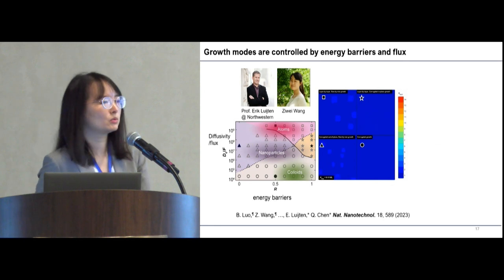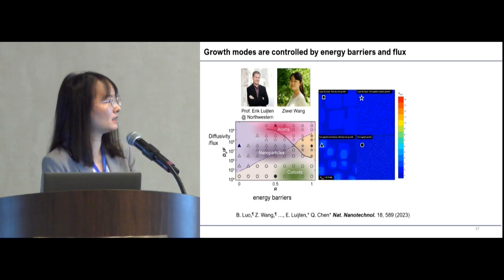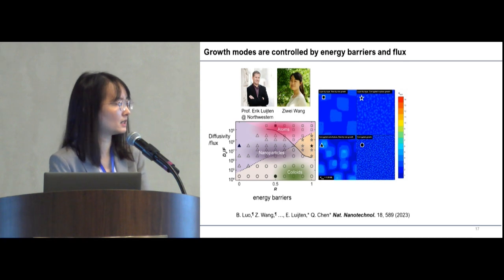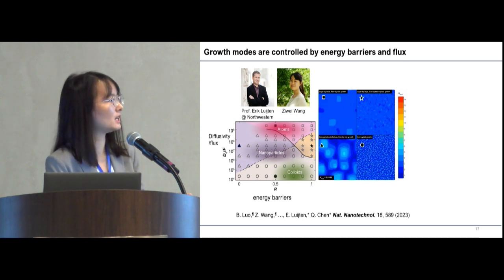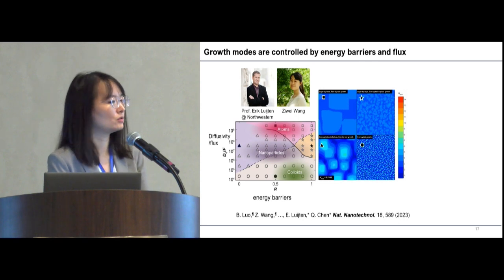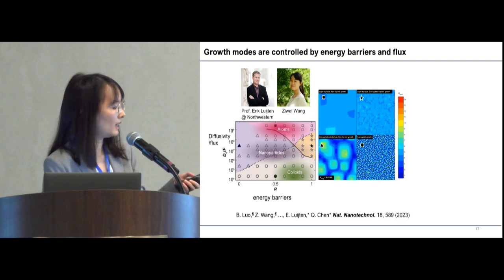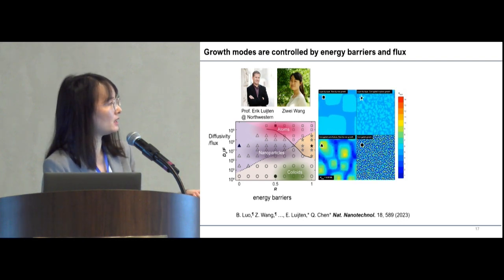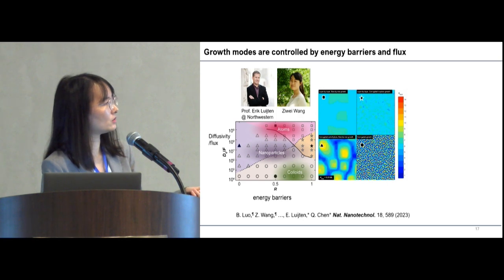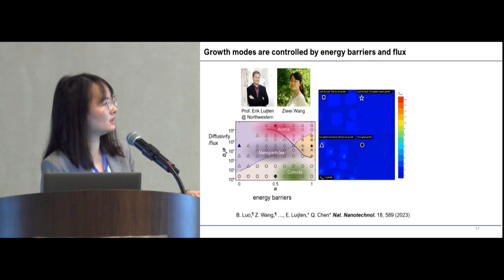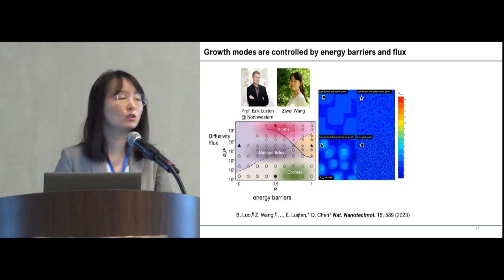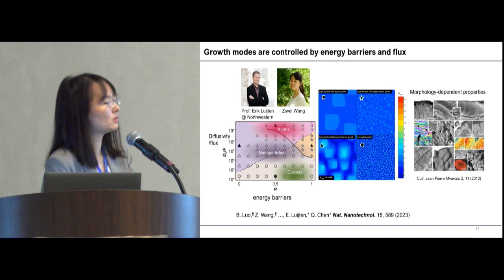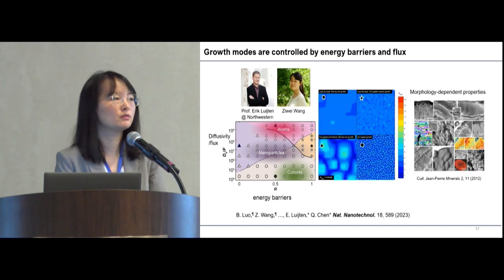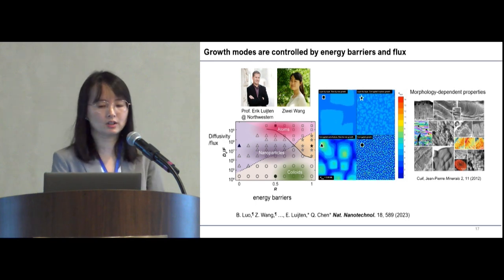So to really understand what is driving these different growth modes, my collaborator, Professor Erik Luijten of Northwestern, was able to come up with this kinetic multicolor simulation, which can reproduce all the four experimentally observed growth modes. And in addition, he was able to provide this phase diagram. So if you look at this phase diagram, building blocks of different sizes, they occupy different regions. Interestingly for nanoparticles, you can occupy all the four growth regions. And that's why with nanoparticles as building blocks, you can have a rich diversity in crystal engineering.